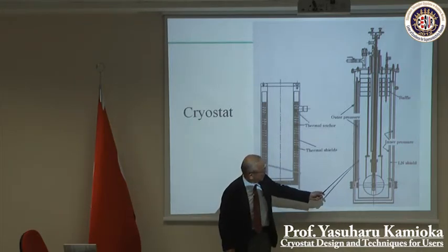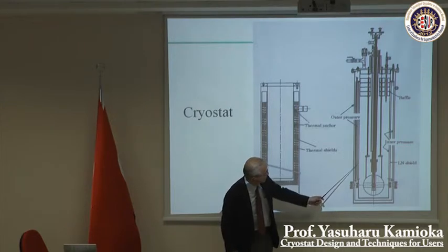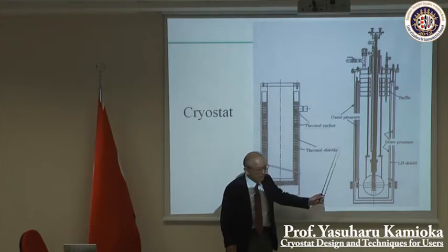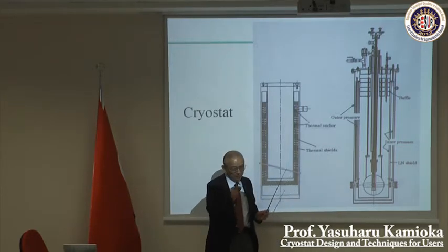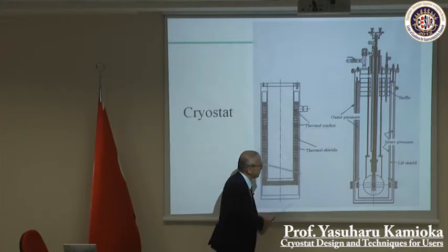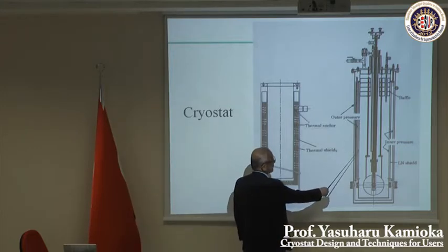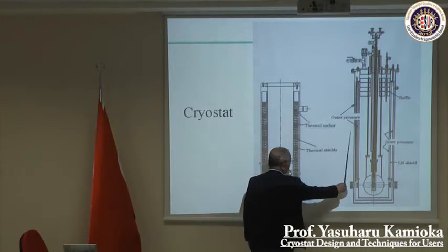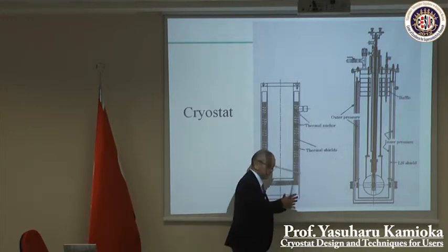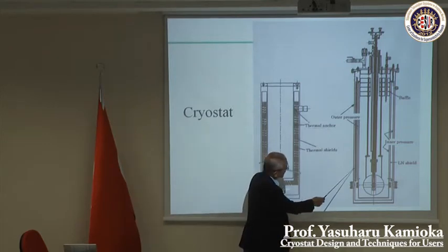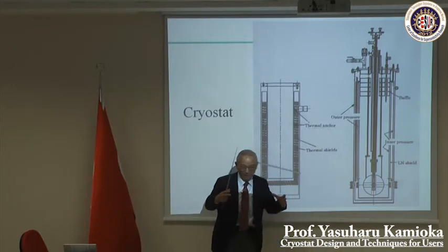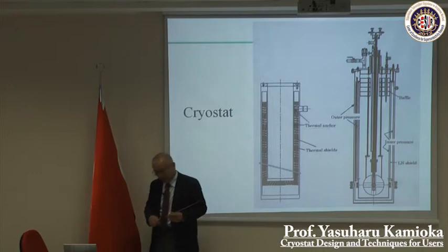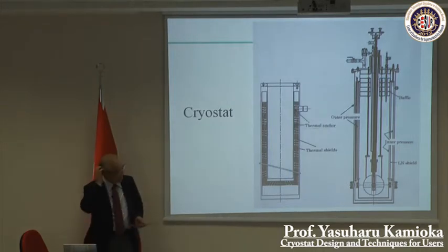Usually we can use a thin plate for the inside of the tube chamber because of inner pressure. But outside, when you have a thin plate and the vacuum sucks the chamber, it crushes. So you have to think about that.